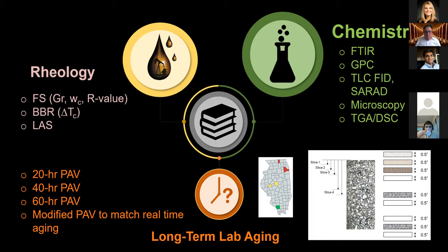Once the rheology and chemistry were determined on the base binders, modified binders, and the modifiers themselves, aging parameters were then applied and the modified binders tested again, using that same protocol. It is understood that asphalt binder deteriorates and is accelerated by aging. It is important to understand how the modifiers will affect the aging of the asphalt binder. In order to validate the lab aging methodology, field cores have been collected and the binder extracted to determine how much the field aged binders compare to the lab aged binders.